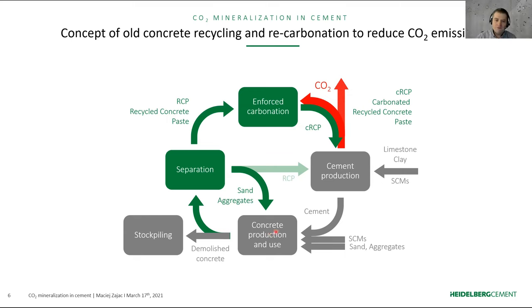And after the service life, the concrete is demolished, and frequently the old concrete is stockpiled or just used for downcycling. In order to assure the circular economy in the cement industry and to allow the sequestration of CO2, we want to change, and we are changing, this way of using the cement. The first step is that we need to recycle our concrete and improve separation of the concrete into coarse aggregate, sand, and a cement paste, which we call recycled concrete paste.